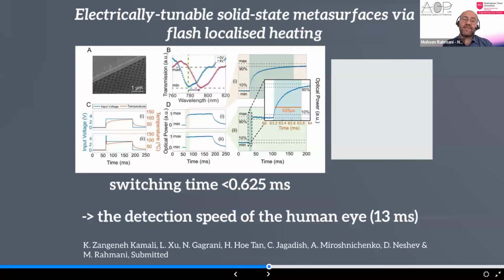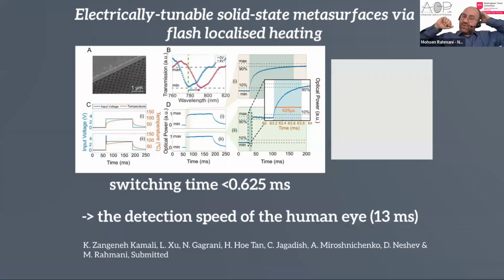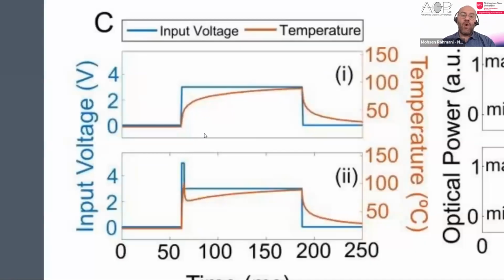And it is a very, very nice research and nice result, which we have just obtained, and it is still under review. Here, what we have done, we have made this membrane of silicon metasurfaces. The reason is written in the paper, so you will see soon. I'm just telling you the main message here. By having an ITO on the top, and connecting it to the electrodes, and then applying the voltage, you can heat up the ITO, which is the local heater on top of the structure. So you can electrically heat up the entire device and your metasurface to get different optical properties.